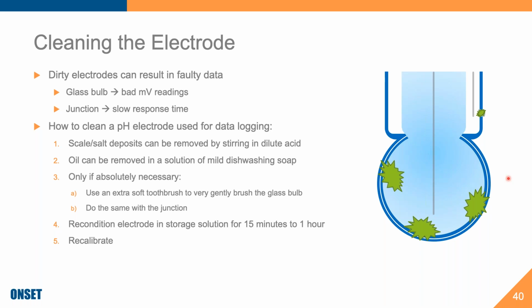Only if absolutely necessary. If for some reason soaking it in an acid or swishing it in some dishwashing soap doesn't work, only if those don't work, then you may want to consider, and I'm very hesitant to recommend this because I come from the laboratory world, using an extra soft, think like a toddler toothbrush, to very gently brush the glass bulb. Sometimes it is necessary to do that. If you have to do that and you're doing it with a super, super, super soft brush, then you might be able to get the dirt off, and you might even get the dirt off of the junction, but soaking this in an acid would really help. No matter what, after you've done this, you must condition. And my recommendation, after cleaning it, you should always recondition an electrode. If you've cleaned it with just some acid, then you can recondition it for like 5 or 10 minutes just in storage solution, just to get a happier hydrated gel layer back.